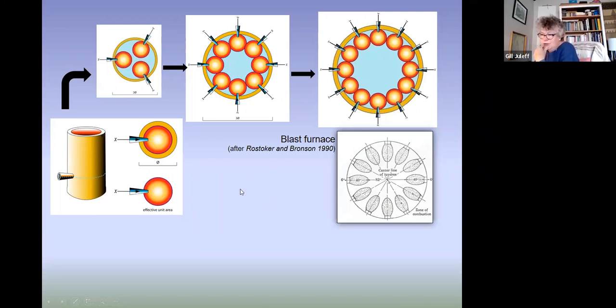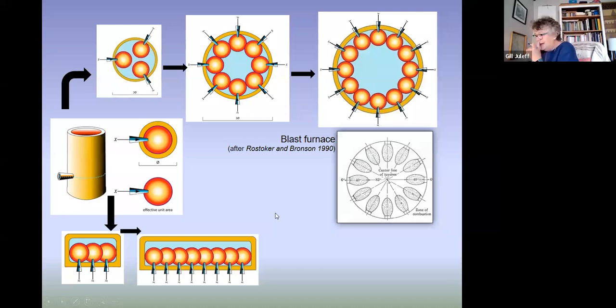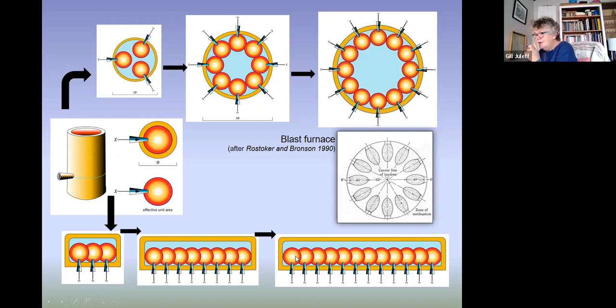If, however, you take a different route, and instead of using a circular model, you use a linear model, and you start to line up your effective unit areas, you're still blowing in the same amount, but you can now double or quadruple your furnace. And as long as your distance between the front and the back of the furnace remains the same, you don't increase your dead area. So for me, that makes a lot of sense. I can see why a linear furnace has a great deal more flexibility than a circular furnace.